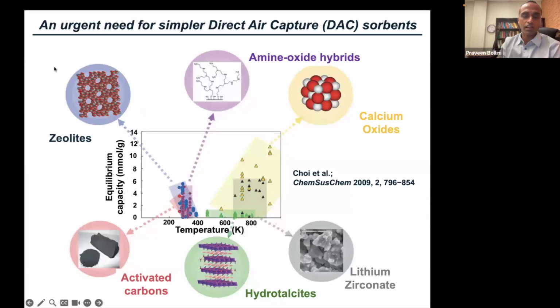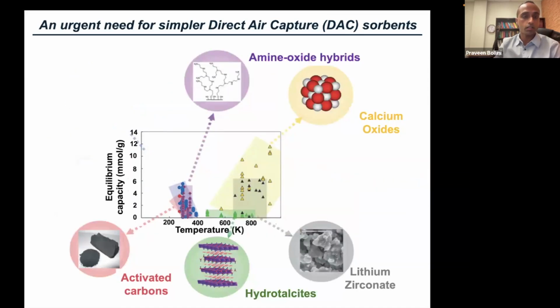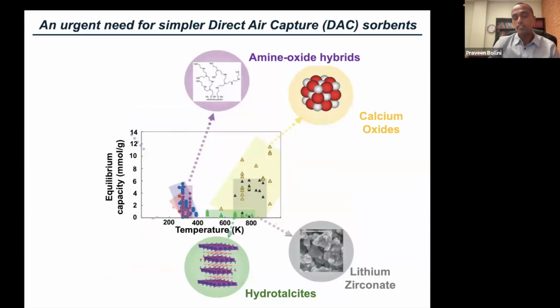For example, if you take zeolites on the top left, there hasn't been a zeolite discovered to date that selectively binds CO2 over water. So when you expose these to humid streams, they generally do not perform well. Activated carbons generally do not tend to be very selective to CO2 over nitrogen. Materials like hydrotalcites and lithium zirconates, either they're dependent on rare earth elements or they tend to only operate at high temperatures that are not very relevant for direct air capture applications in a lot of cases.